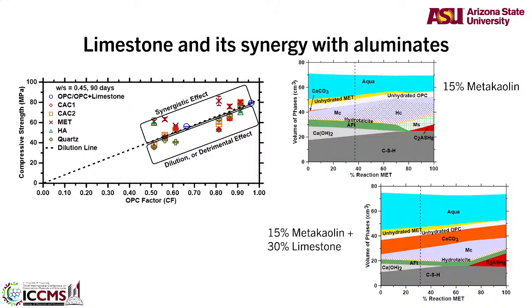So that's the whole idea, and what I'm showing here is some thermodynamic simulations. Metakaolin is a very reactive aluminate, and you can see here mono and hemicarbonate formation, plenty of monocarbonates and hemicarbonates. And when you add metakaolin plus 30% limestone, this is your typical LC3, right? 15% metakaolin, 30% limestone, 5% gypsum. That's your LC3 cement, if you know limestone calcined clay cement. And you will see lots of monocarbonate formation. Hemicarbonates are converted to monocarbonates as well. So you get system stability that way.